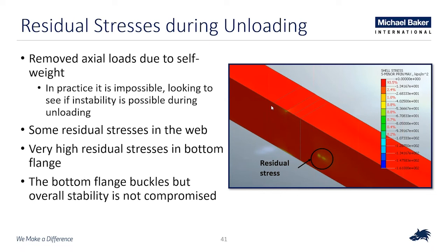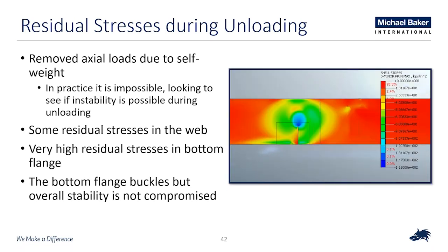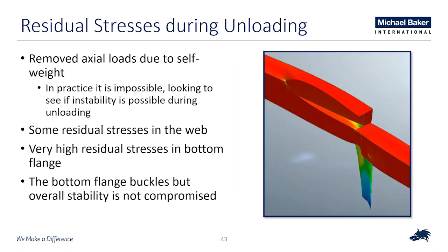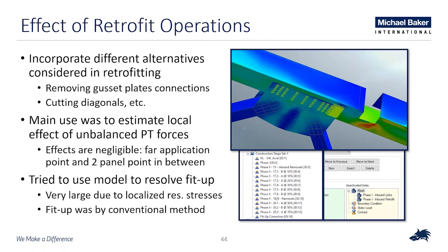So the gusset plates are removed, and those are basically the extent of the residual stresses in the web plate. However, obviously, in the bottom cover plate that was almost cold worked, you did have very significant residual compressive stresses forming. When you were to unload the tie completely, as shown in the next slide, that bottom cover plate will completely buckle, but the overall stability of the tie wouldn't be compromised. Once we reached that conclusion that we could safely unload the tie without any concerning local instability issues, we used this local model to incorporate the different alternatives considered during the retrofit.